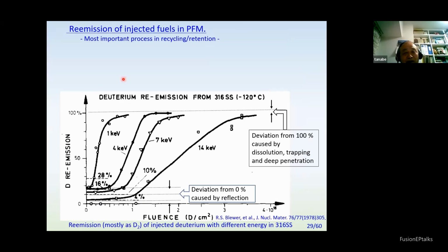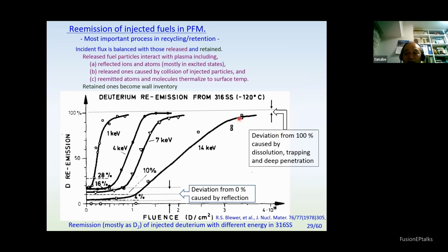The most important experiment is the re-emission experiment, where they inject high energy or low energetic deuterium ions - in this case into stainless steel - and then they are re-emitted from the surface. High energy ions go very deep and slow down, low energy ions only go shallow and come back earlier. There are also differences with the incident energy, due to differences in the reflection coefficient. Also, deviation from 100% is due to deep penetration or trapping in the materials.